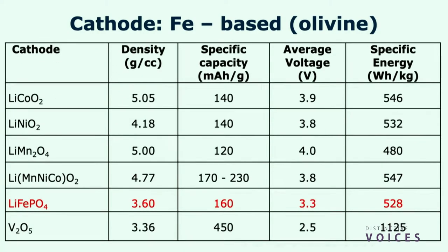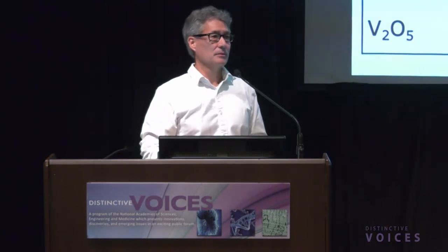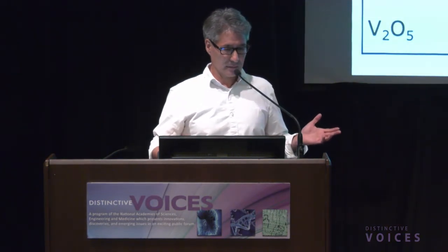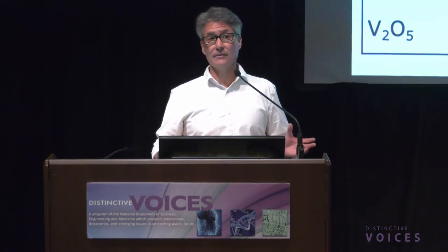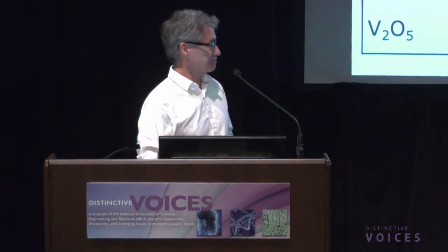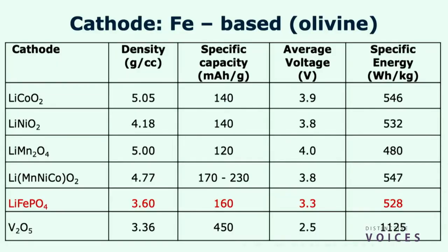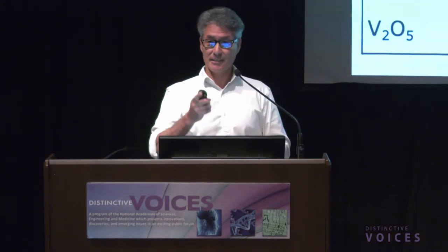Why aren't we going exclusively to lithium iron phosphate? It's because the voltage is relatively low, right? It has good capacity, low density, but its overall specific energy is kind of low. But, you know, this is going to be a game of trade-offs. If we can't get access to nickel and cobalt, or there's just not enough, it's too expensive, then we have to think about alternatives. Okay, so really quickly, A123 Systems was a beneficiary of a lot of taxpayer money, and they made lithium iron phosphate happen, but it's no longer in the United States.